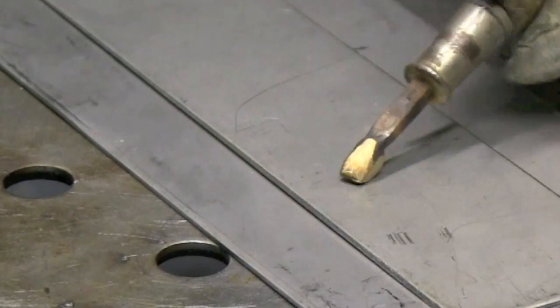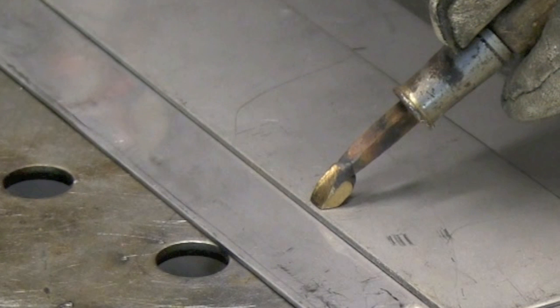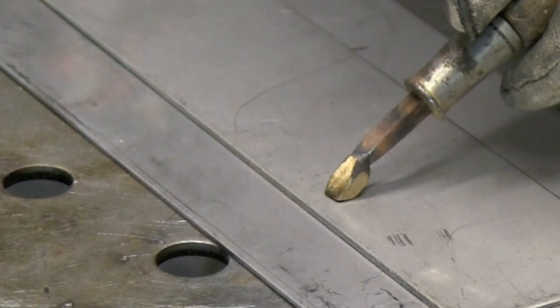And because of that silicon bronze, number one, it won't contaminate the stainless with carbon steel. Number two, it draws heat out really quickly, and you can put it right dead next to where you're going to put the tack, and it'll prevent the puddle from wicking over and melting off that edge. And this is especially important when you start getting thin sheet metal like 30 thousandths, 20 thousandths. This becomes really handy and helps a lot in getting tiny tacks on there without peeling away that corner with the amperage.